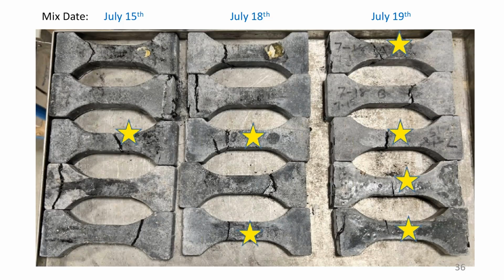Now, we weren't really concerned about compression. We were concerned about tension. Will the material that is truck mixed in the field, something that we had not done before, achieve strain hardening behavior? That was a big unknown for us. So we asked Bill to take these types of samples for us. These are tensile coupons, which are put in a machine and pulled apart. But because Bill's team had not done these before, whereas we do these on a daily basis, many of them failed incorrectly. They failed at the head, or they got crushed at the head. But there were 7 that survived, from which we got the tensile information.